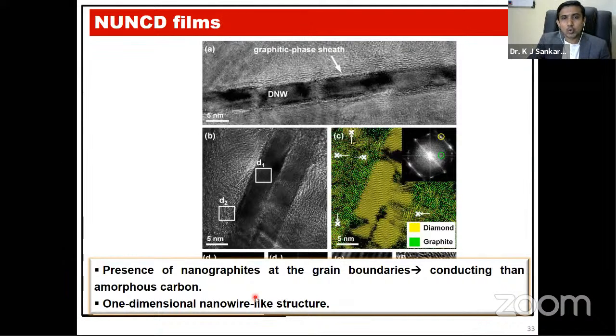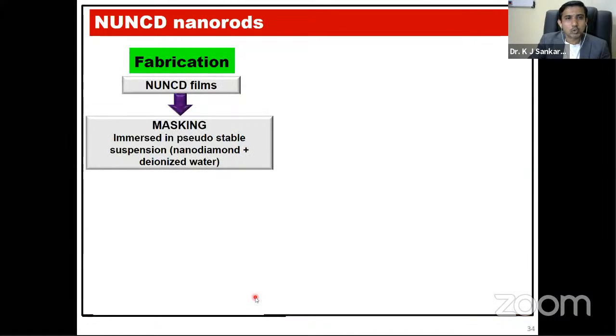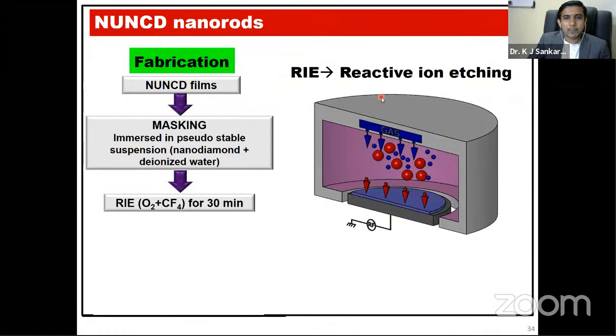But can we make one-dimensional nanostructures? The following slide shows how to make the NUNCD nanorods. Here we have grown the NUNCD films with wire-like morphology. Then we mask these NUNCD films using nanodiamond powder with deionized water. The masking happens by the ultrasonication method, and then we follow the reactive ion etching process using oxygen and CF4 plasma.